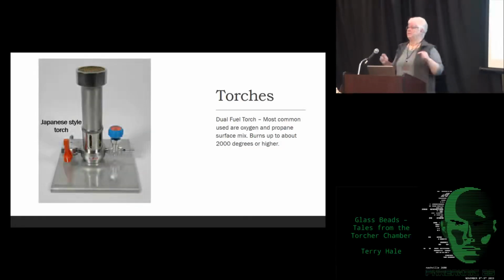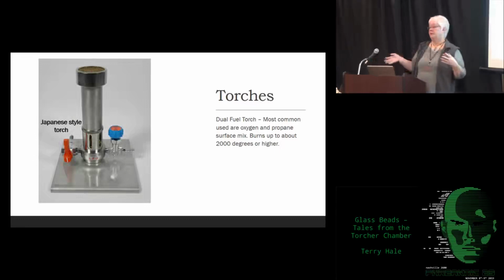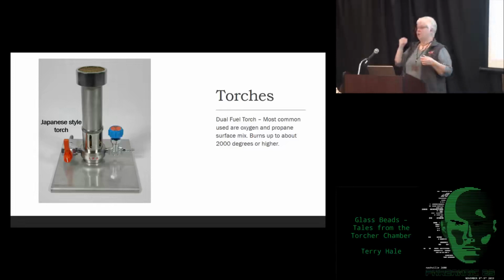And these are interesting. I threw this in because the Japanese have a kind of glass that's a totally different COE than anybody else. It's got a very high COE, so it stays malleable for a long time. It's so soft when you melt it that you can basically hold it over a candle and it'll start to move. It won't melt completely, but it will actually move. And we're talking the rods like they're going around there.